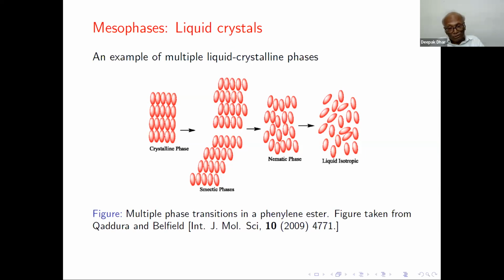And then when you decrease the density, it goes into some other phase, which is called the nematic phase, where the translational symmetry is fully restored. The system is translationally invariant. There is no layering, but there is still orientational order. So molecules are preferably in one direction rather than another. And in isotropic liquids, the orientations are random and the positions are also random, and there is no broken symmetry. Okay, and so these are the different phases.